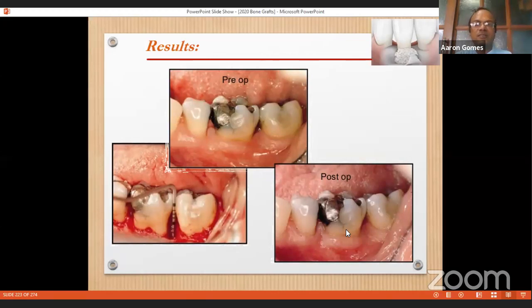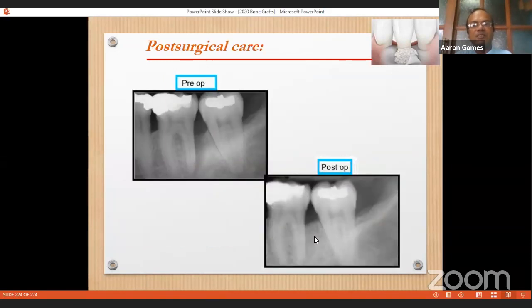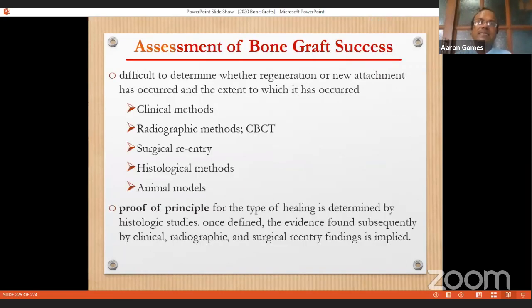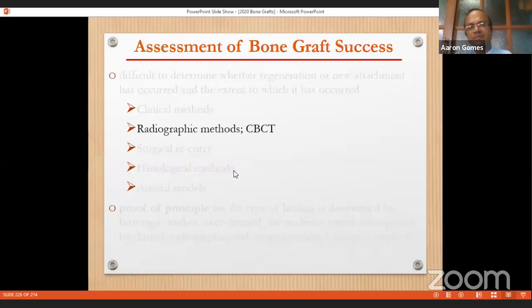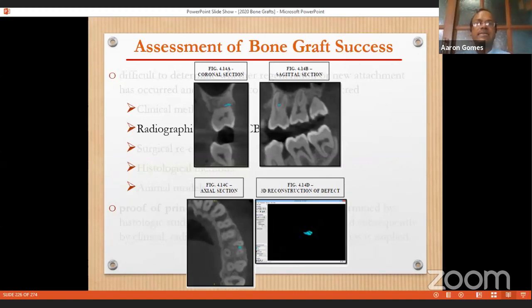Pre-operatively to post-operatively, you see that you get good results, and radiographically also you will assess, and you have seen that you have got good bone fill. But are these the methods to see whether your graft is successful? Clinical methods and radiographic methods? No, actually probably CBCT, surgical re-entry, histologic methods, and animal methods. When you talk about CBCT, if you use the 3D sectioning of the models of your CBCT, your DICOM images, and you use software like ITK-SNAP, you can do a 3D reconstruction by using the various segmental sections of that defect. So you can do a 3D reconstruction of the defect prior to using the bone graft, and probably 9 or 12 months after using the bone graft, and you can actually appreciate how much this has helped.